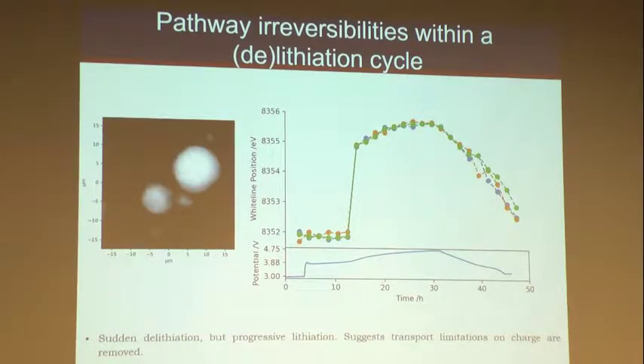And so this is an example where all particles went at the same time. It's a different measurement. They go at the same time, they keep going a little bit while you're charged, and when you start discharging, then they go progressively. And we think that this is because that insulating layer is gone, and now lithium can move freely in and out. And then you're much closer to a thermodynamic condition. You're not in conditions that are kinetically imposed by transport, which is critical in a battery.